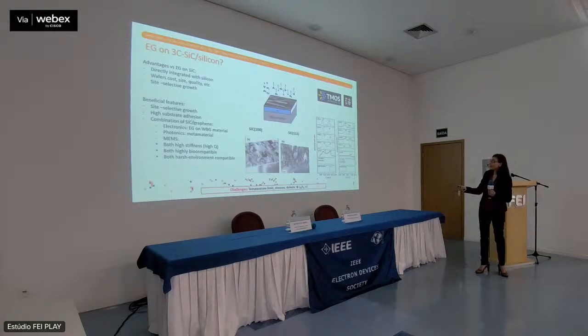Challenge number one: if you do a cross-section of the system, silicon carbide on silicon, you would already see that the silicon carbide, which is this one, these are different surfaces of silicon where we grow silicon carbide, has an enormous amount of defects. Because there is a huge lattice mismatch, 20% between the carbon and the silicon, which is really hard to work with, we can't get rid of these defects. And as you know, if you use this defective template to grow something, you will get defects. There's nothing you can do about that. And this has mostly always been the case.